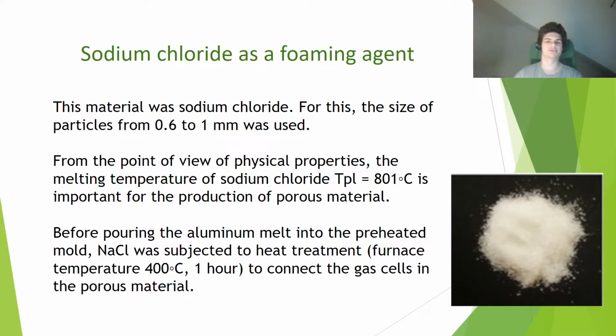Sodium chloride as a foaming agent. This material was sodium chloride. For this, the size of particles from 0.6 to 1 millimeter was used. From the point of view of physical properties, the melting temperature of sodium chloride is 801 degrees Celsius, which is important for the production of porous material. Before pouring the aluminium melt into the preheated mold, salt was subjected to heat treatment to connect the gas cells in the porous material.